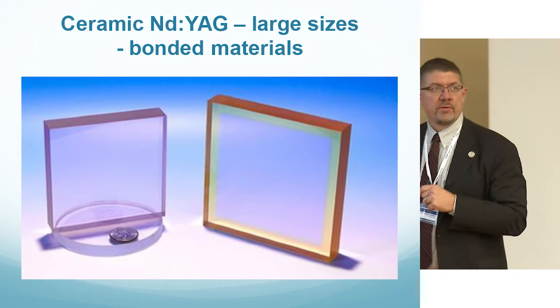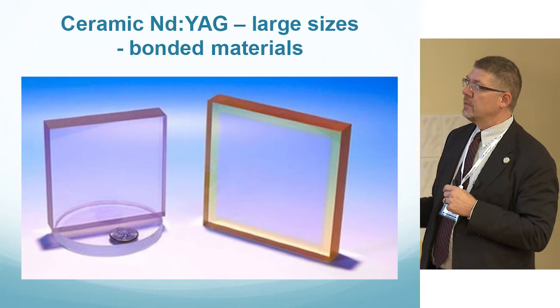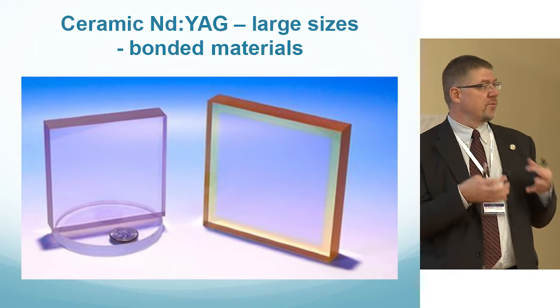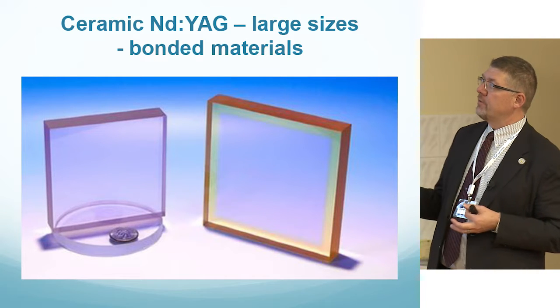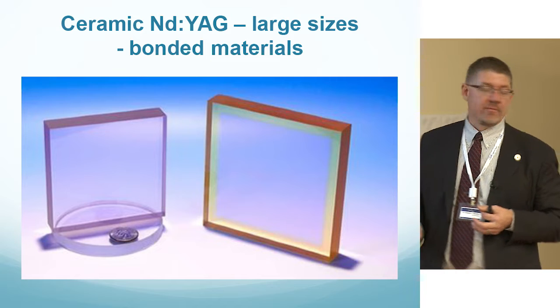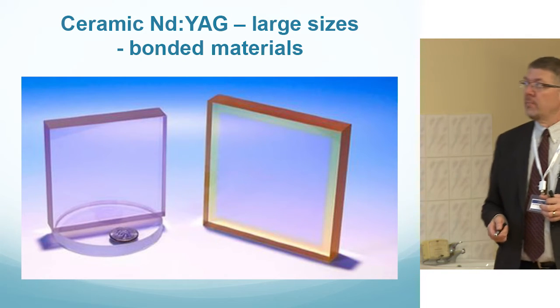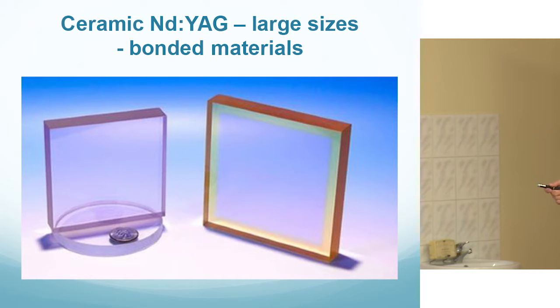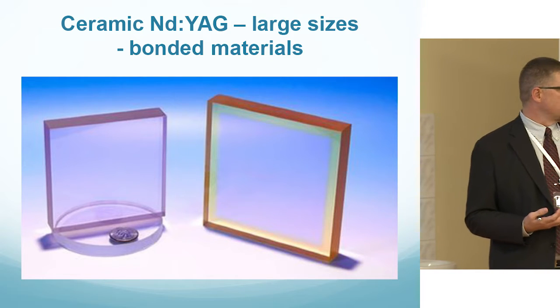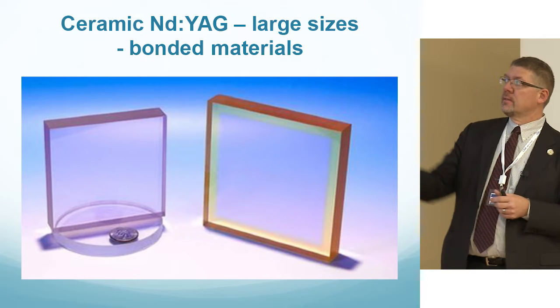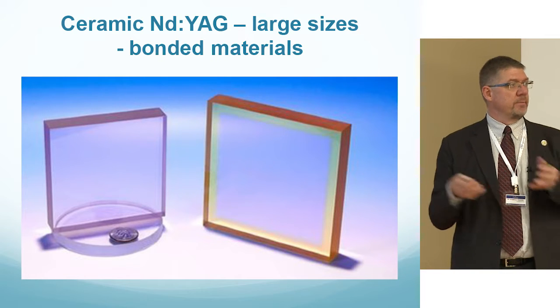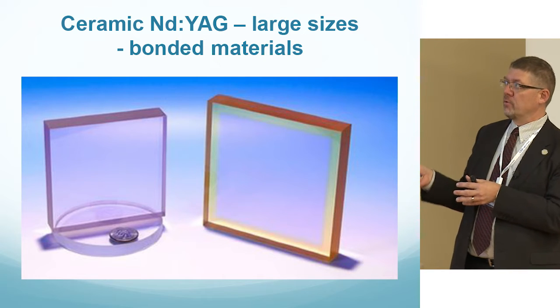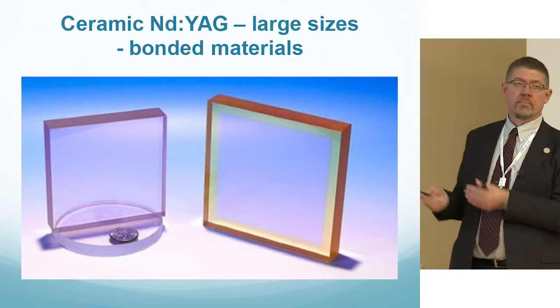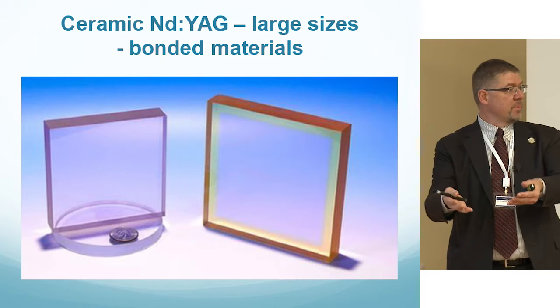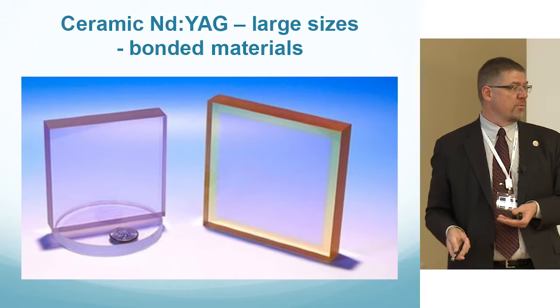And then one of the other unique properties about the ceramics, you're able to bond similar materials to the ceramics in the green process while the powders are still wet. This is a 10 centimeter by 10 centimeter by 11 millimeter slab of neodymium YAG made by Konoshima. They've also put a 10 millimeter band of samarium doping all the way around it as an ASE, amplified spontaneous emission suppressor. So in those big lasers at Livermore, they can substitute these plates in now of Konoshima ceramic YAG. What they did was they took the purple plate with the neodymium and the samarium plate in a wet form, put them together, put them in the furnace simultaneously, heated them up, cooled them down, and it came out as one uniform piece.